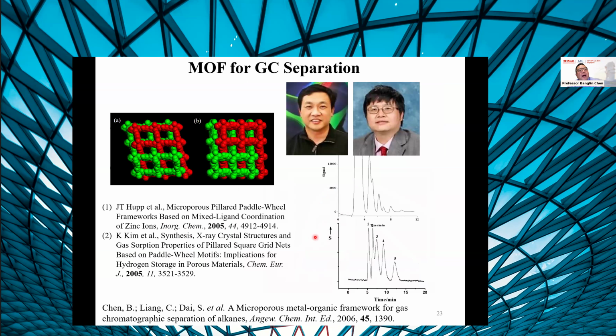This is our main part on the gas separations. And we synthesize this material, and the pore is around 4 angstrom, and we realize that these 4 angstrom can exactly recognize the linear part of alkane. So we pack the column for GC separation, so it can separate natural gas and also hexane and pentane and isomers.